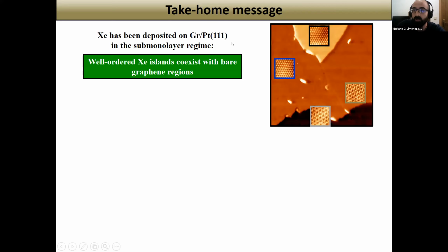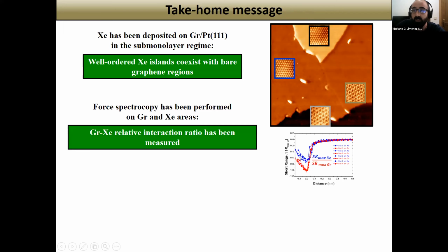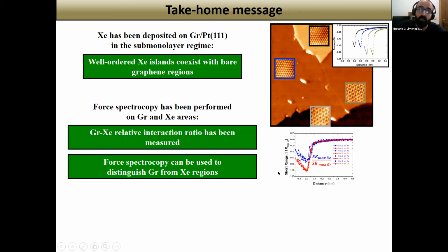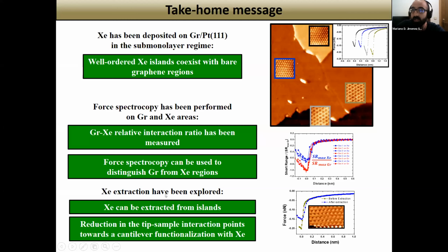So, as conclusion and take-home message, we have deposited xenon on graphene in the submonolayer regime, and we have observed that we have separated regions of xenon and graphene. We have performed force spectroscopy on graphene and xenon areas in order to measure the relative interaction ratio between the xenon and the graphene, and we have shown that force spectroscopy can be used to distinguish xenon from graphene without need of atomic resolution. And finally, we have explored the xenon extraction, showing that xenon can be extracted from the islands, and that after this extraction, there is a reduction in the tip-sample interaction that points towards a cantilever functionalization with xenon.